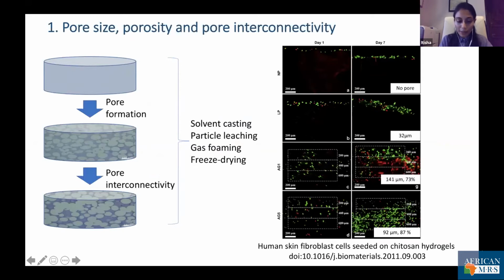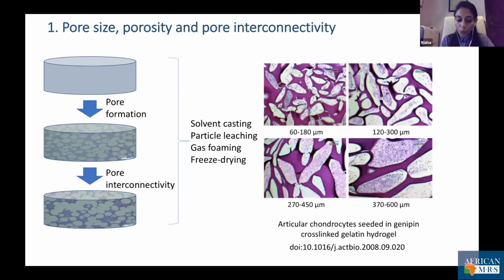So in this example, the size and porosity of the chitosan hydrogels have been shown to influence cellular infiltration and viability of human fibroblasts. An increase in the pore size from 32 to 92 increased cellular infiltration, and high porosity also improves cell viability so that nutrients can pass through and reach the inner cells within this structure. Other studies also show bigger pores improve rate of chondrocyte proliferation in gelatin hydrogels and improve GAG synthesis and collagen synthesis. So it shows that the porosity plays a major influence on cellular behavior in a hydrogel system, which is very important to cater for when developing these types of hydrogels.